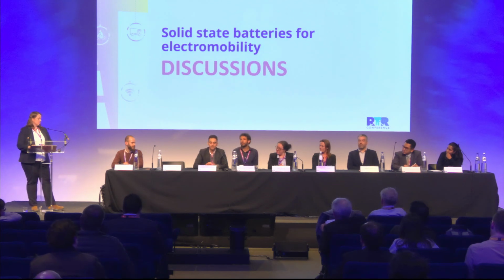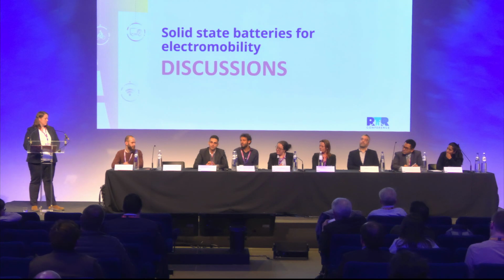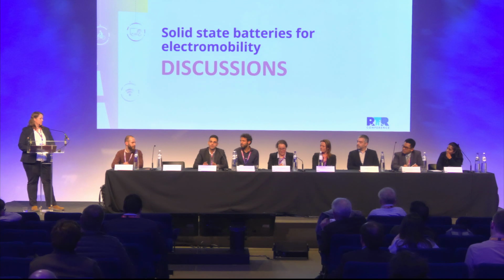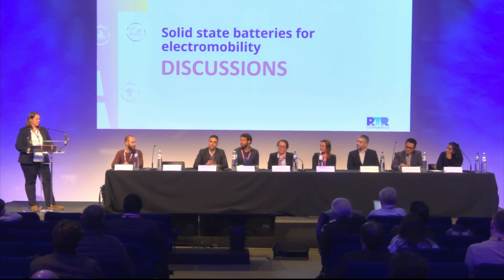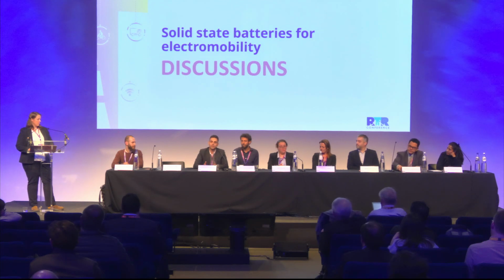But then when you make the processing, here is the missing information for the processing. When you make the electrodes, a lot of additional parameters kick in, and what you have made before with the coatings, where you have protected, for example, your cathode and solid electrolyte and so on, when you make the electrode, you have to re-engineer that again.